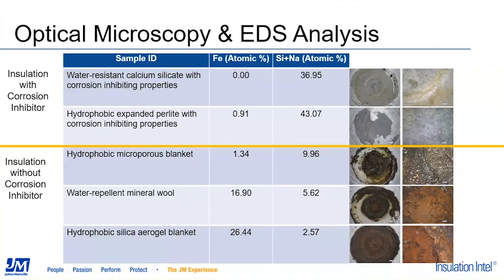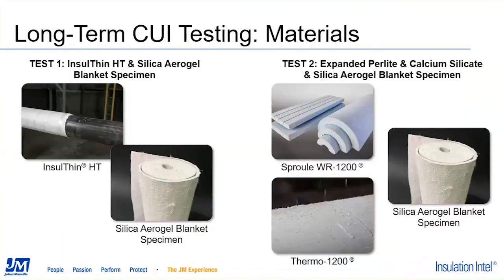Whereas the last two products on the list, the water repellent mineral wool and the silica aerogel blankets, both showed very high percentages of iron on the surface of the coupon, indicating significant levels of corrosion and very low levels of silica or sodium ions. So again, showing very little protective compounds being present in the materials.